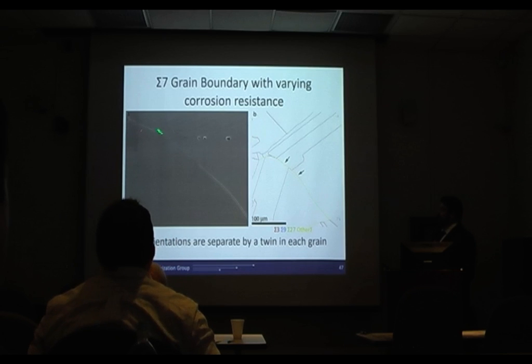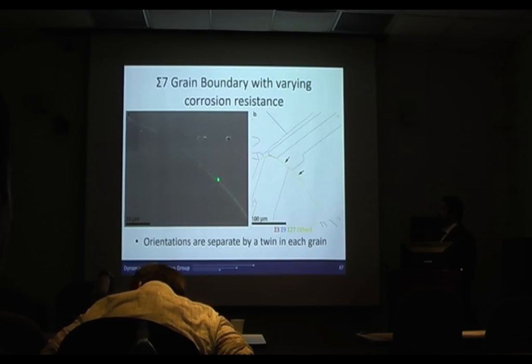Moving on, we also had a pair of sigma 7 grain boundaries. Those are shown in yellow here, and you can see that on the left, one did not corrode and one did corrode. They're actually separated by these two twin orientations on either side of the grain.